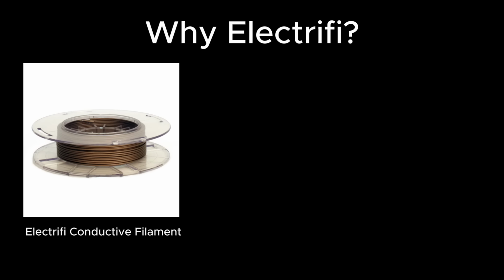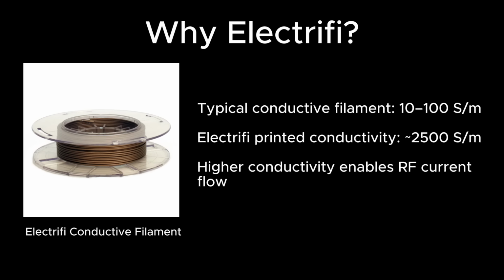To achieve this, the researchers used Electrifi conductive filament, a copper-based composite material designed for fused filament fabrication. Most conductive filaments based on carbon or graphene fillers typically have conductivities in the range of 10 to 100 Siemens per meter. Electrifi offers significantly higher conductivity. In this study, the measured conductivity of the printed Electrifi structures was approximately 2,500 Siemens per meter in the operating frequency range between 0.72 and 2.5 GHz. This higher conductivity allows Electrifi to support the RF currents required for antenna operation, making it possible to fabricate microwave devices using standard desktop 3D printing equipment.